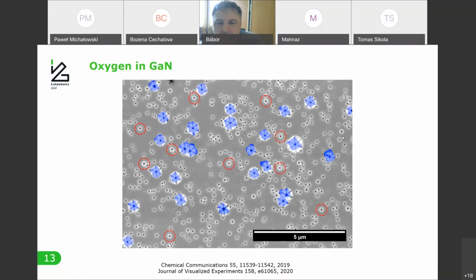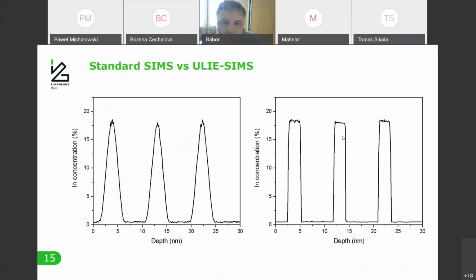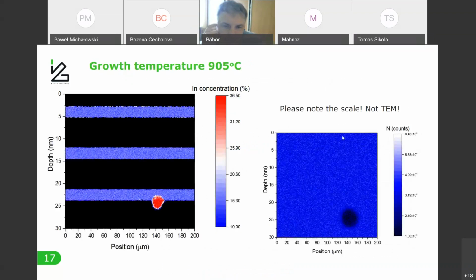The problem is that when you form the image by deforming the beam with these mechanical parts, these square stencils, you can only decrease the size so much. Slightly below 1 micron is typically the best you can get. And here, for example, I actually don't expect this precipitate to be 20 micron thick. I think there is some agglomeration of smaller precipitates here, but they are blurred together.